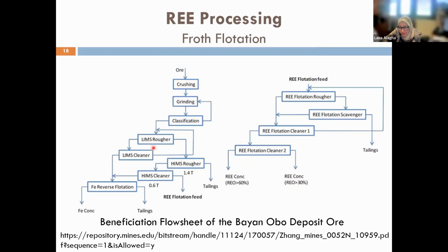Physical beneficiation includes the use of low intensity magnetic separator and high intensity magnetic separator. So after crushing, grinding, and then size classification, the feed goes to the LIMS, we call it LIMS, rougher to remove magnetite, and then the concentrate is cleaned by the second stage of magnetic separator, and then followed by high intensity to remove hematite, and then another cleaning stage for the HIMS cleaner, and then after that the feed goes to the flotation, which also involves rougher and scavenger. So the scavenger circuit is usually utilized to increase or maximize the recovery, while the cleaning is to improve the grade or the quality of the concentrate.